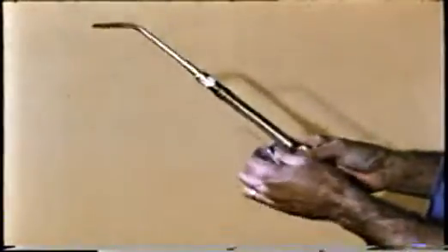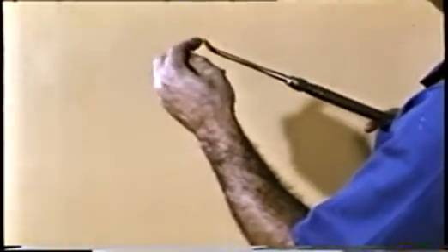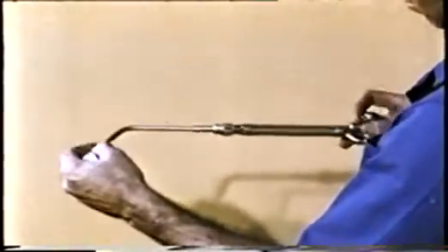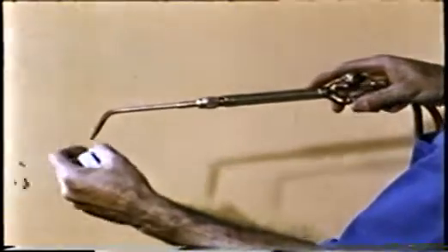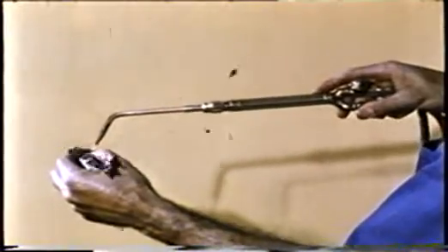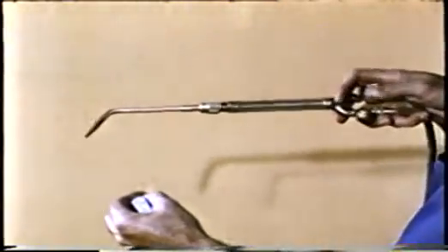Periodically, it may become necessary to check and readjust the oxygen needle valve for a precise neutral flame. A split flame indicates a dirty or clogged tip. Also, a definite change in sound might be heard. If this occurs, clean the tip orifice with the appropriate size tip cleaner or drill. Be sure the oxygen needle valve is cracked open to prevent the dirt from entering the tip.